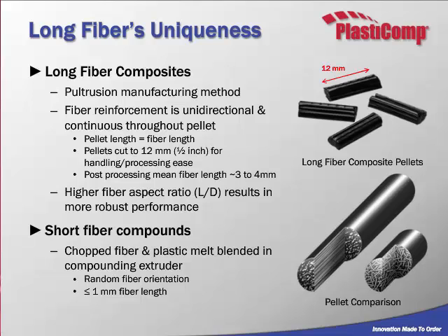If you compare that against how a short fiber material is processed, short fiber will start with chopped reinforcement that is already typically less than 12 millimeters in length. It is then added into an extruder where it's combined with the polymer of choice, and by the time it exits and is formed into a pellet, the length of the fiber is typically lower than 1 millimeter.